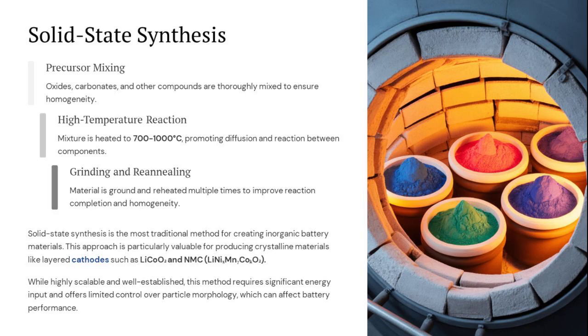For example, to synthesize the common cathode material LiCoO2, we might mix Li2CO3 and Co3O4 in a stoichiometric ratio and calcine at around 800 to 900 degrees Celsius. The reaction proceeds through the decomposition of the carbonate, releasing CO2, and the subsequent formation of the layered oxide structure.